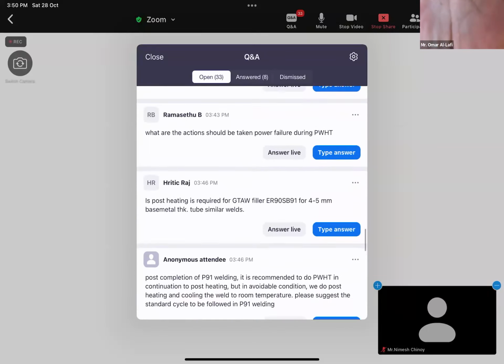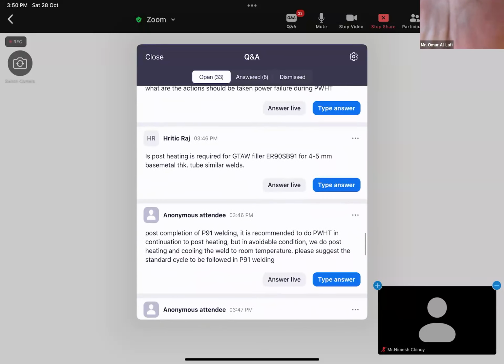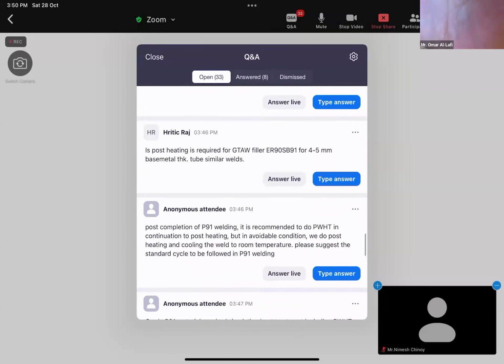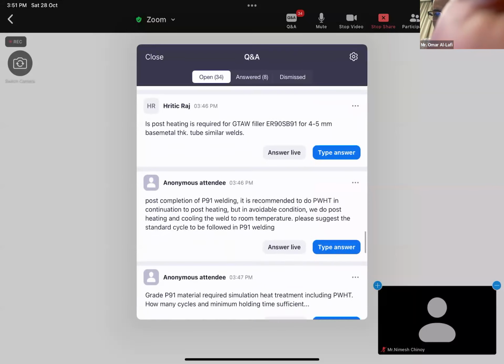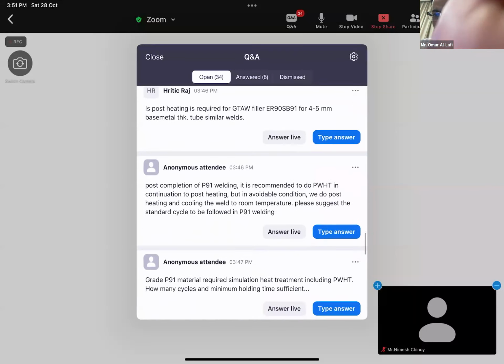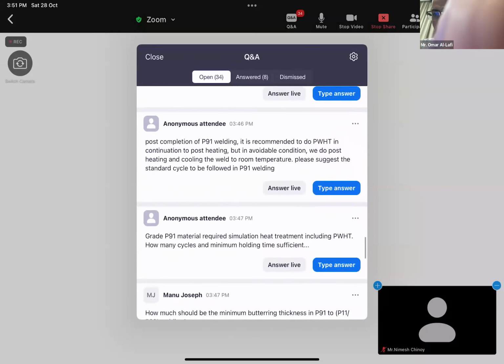Is post heating required for GTAW base metal tube? Post heating in P91 is optional. It's okay, you can do it. But when you have low hydrogen electrodes, you can waive it. The most important thing in P91 is not the post heating or the post baking, but the post weld cooling. Post completion of P91 welding, it is recommended to do PWHT in continuation to post heating, but in unavoidable conditions, we do post heating and cool the weld to room temperature.